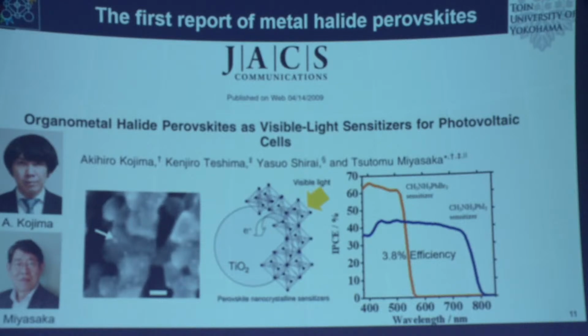That's quite interesting. The big issue with this cell they made was that they used an electrolyte as the redox couple. This takes the positive charge, or the holes, off these perovskite crystals, and that same electrolyte actually dissolved the crystals. So they could put the cell together and measure it, but it literally lasted 10 seconds. People didn't really follow it very much.